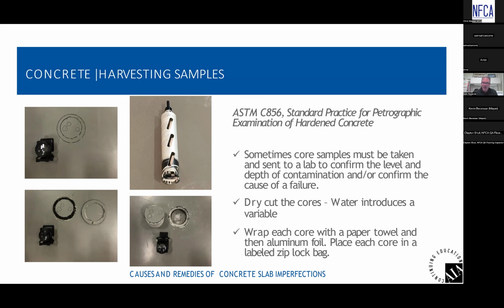And sometimes you need reflection of light. Sometimes you need a flashlight or maybe your phone flashlight to try to see that. But you want to circle the areas on the surface so that the lab can identify what you're seeing on site. And then we drew the perimeter. We have a diamond hole saw for cutting the core. We traced the perimeter of the diamond hole saw and then actually measured the thickness of the diamonds and then drew an inner circle and scribed the flooring and removed the flooring so that the diamond hole saw could sit directly on the substrate beneath the flooring. That way, we're not tearing the flooring off when we're trying to harvest the core sample with the diamond hole saw. So that's a critical piece of having the complete assembly intact.